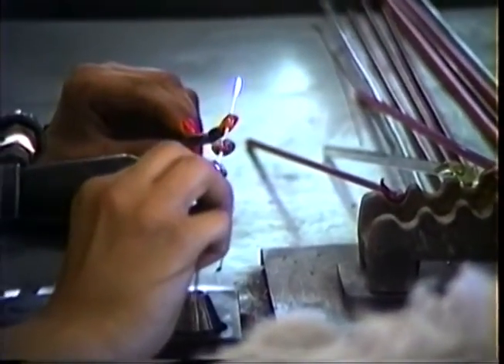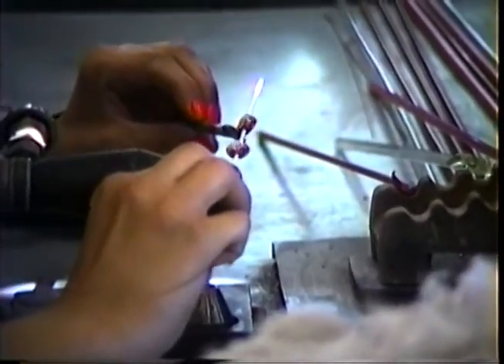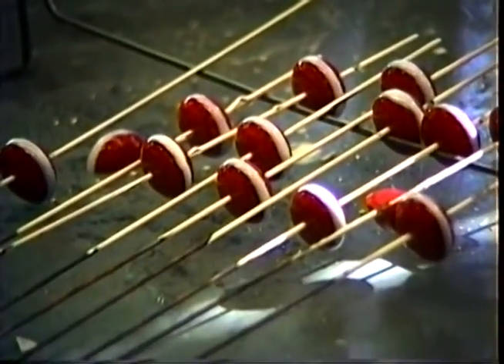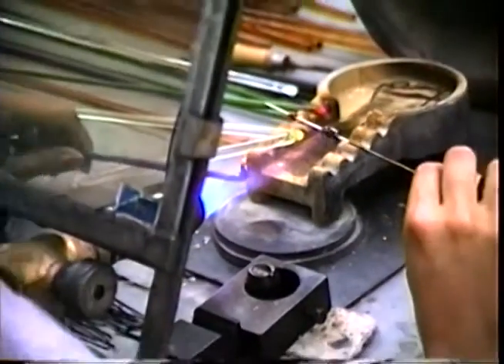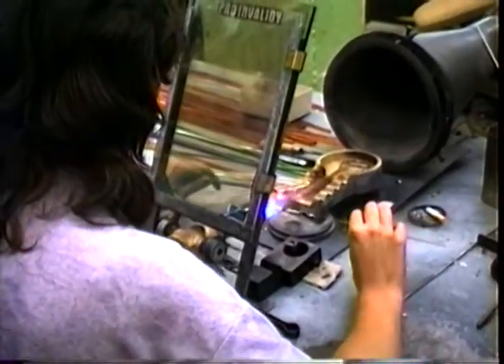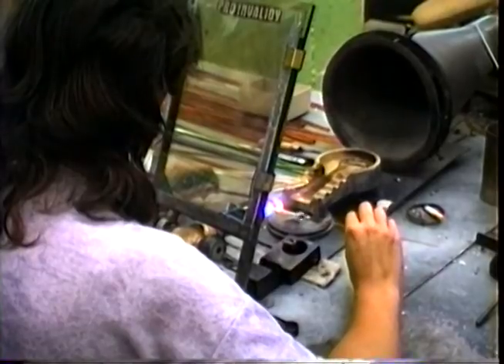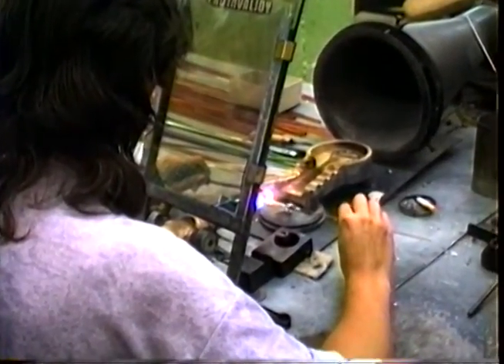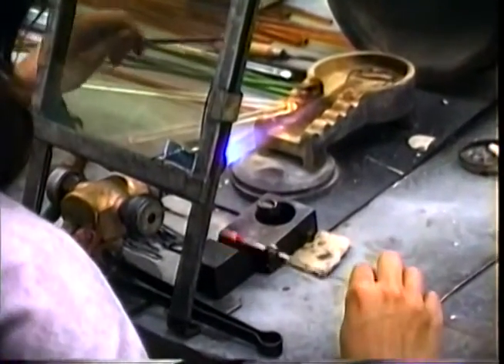She's using a nice little paddle for shaping. These beads are air-cooled. You can see the rods are preheated. The vacuum cone pulls heat and fumes away from the worker, not up past the face to a system overhead. These cast iron rod rest forms are used everywhere in Bohemia. Each bead has molds for shaping that are specific to that design.